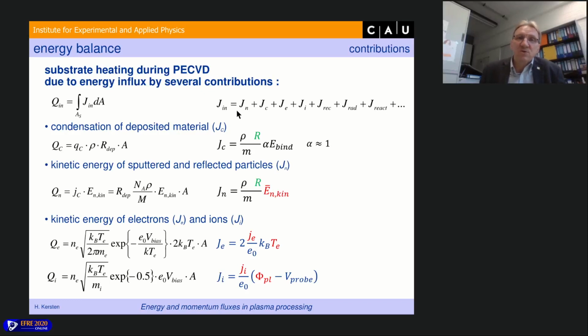And you can try now to identify each of these values by an equation. For instance, for the condensation, the heat of condensation depends, of course, on the deposition rate, on the density of the growing film, and the specific energy of condensation of this material, if it is a copper film or aluminum film or whatever. Or if you look at the kinetic energy of the electrons or ions, for the electrons, you just use the Boltzmann factor and, of course, the energy of the electrons. And for the ions, you use the Bohm flux and the bias voltage, which influences the energy of the ions.